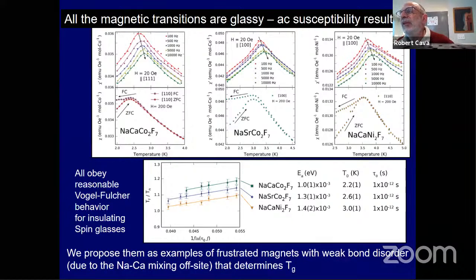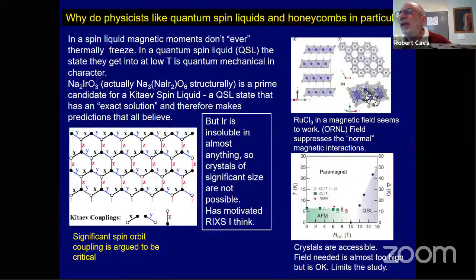And the only reason these do it is because you have disorder on the A site, the off-site thing. Otherwise, they could get very, very cold before anything happens. Okay, they're already 1/100th of their interaction temperature, which is a civilized rate.